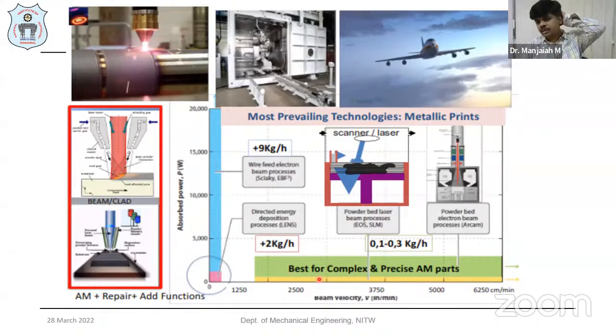With the powder bed fusion process, the more complex parts can be made, with the best complexity. And with precise components, you can go with the SLM process or the EBM process from Arcam and others. But the rate of production is less, only 0.1 to 0.3 kg per hour. The production rate is very low. But if you need high precision and more complexity, then you can go to these kinds of technologies.